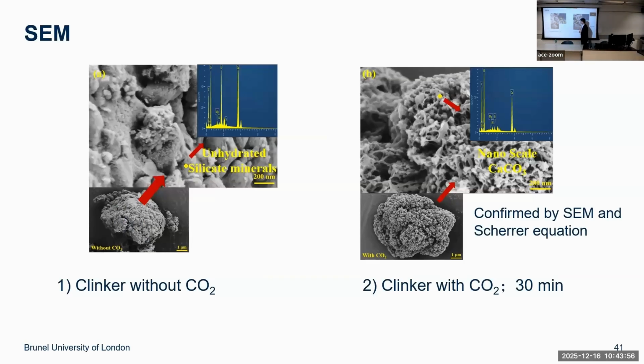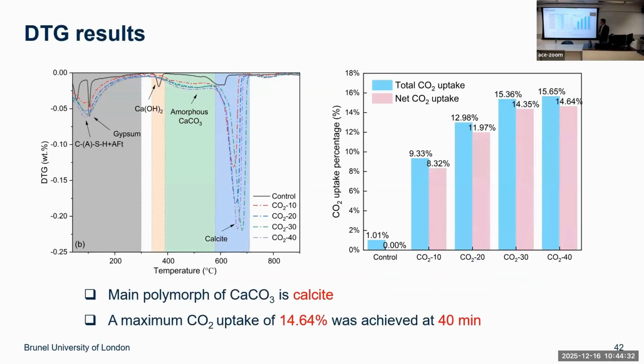We also looked at the microstructures of the clinker without carbon dioxide and with carbon dioxide injection. You can see that you have much smaller particles. Looking at this 1 micron scale, the particles are less than 100 nanometers, which in a way proves it's nano-sized calcium carbonate. Our paper's reviewers question whether it can prove that, and we need other analyses to further prove this generates calcium carbonate on the nano scale. We also do thermogravimetric analysis to find out how much carbon is sequestrated.